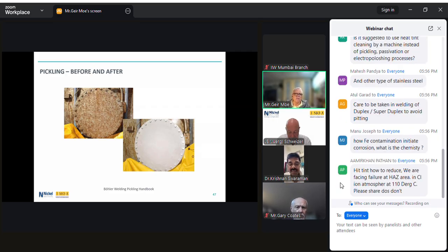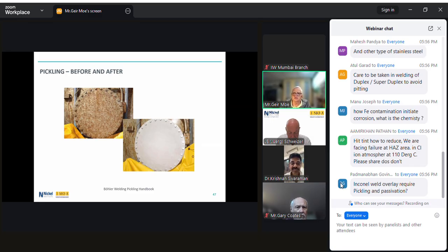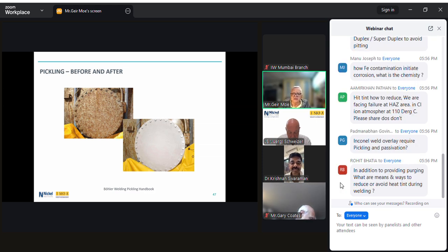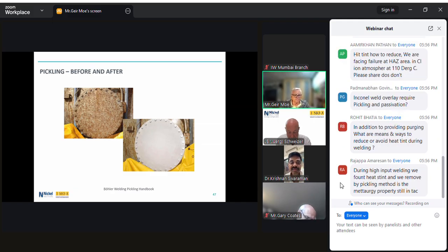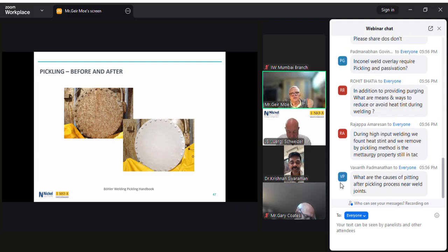passive oxide film. If the contamination is just kind of minor, just some carbon steel contamination from, say, grinding, well, then you would use, say, a nitric or a citric acid to remove that from the surface. And that's true whether it's a 300 series stainless steel, whether it's a 200 series stainless steel, whether it's duplex, and even 400 series. The only thing is to recognize that the corrosion resistance of the stainless steel will determine the strength of the pickling acid that you would use to do the pickling or the passivation. But it applies to all grades of stainless steel.